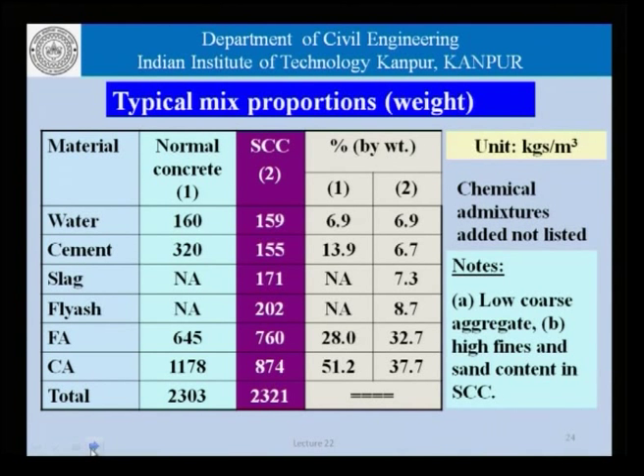self-compacting concretes. Now, if you look at the typical mix proportions by weight of normal concrete and of self-compacting concrete, these numbers here are those for a normal concrete, and these numbers are for a self-compacting concrete. Now, if you look at these numbers, these are the proportions in mix 1, that is the normal concrete, and the self-compacting concrete, and we are able to see the proportions by weight.